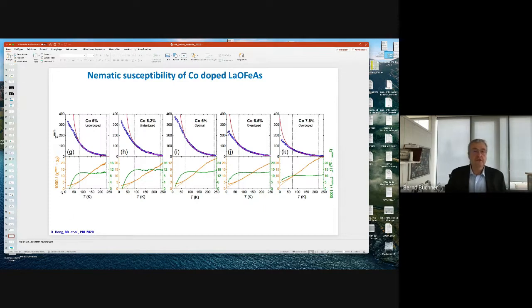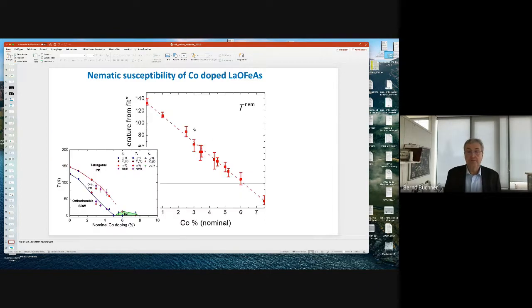So we did that for all these crystals, and you always see this Curie-Weiss-like behavior. You see that this Curie-Weiss temperature becomes smaller, approaches 0 close to 6% doping, and then it becomes even negative. So 6% doping is the system with the highest Tc. If I now plot these Curie-Weiss temperatures from this fit as a function of doping, you see it hits 0 just at the 6% doping. Just at the system which is a good superconductor, the fitting tells us this is the way the nematic instability decreases and approaches 0. What you get from this Curie-Weiss temperature is, of course, the relevant energy scale for these fluctuations.